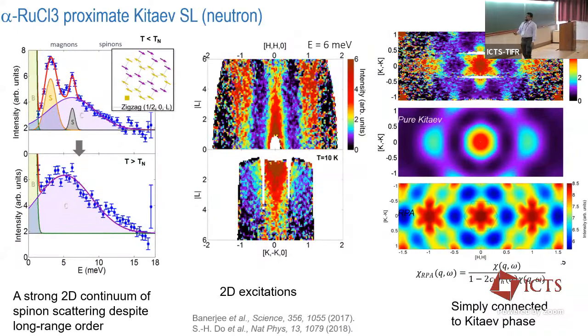So what we did was neutron scattering, where we measured intensity versus energy at temperatures less than the Néel temperature and temperatures greater than the Néel temperature. What we found is that at temperatures less than the Néel temperature, we see these spin wave modes, marked S, sitting on top of a continuum, and above the Néel temperature, you just have the continuum of scattering. This is L versus K. So you see this rod-like scattering spectra, which means that this continuum is mostly confined in each plane. So even if you have a 3D material, it doesn't really matter. You're still all in plane.